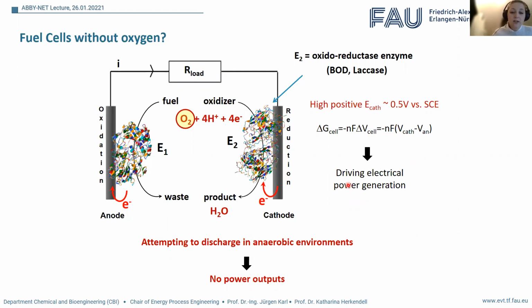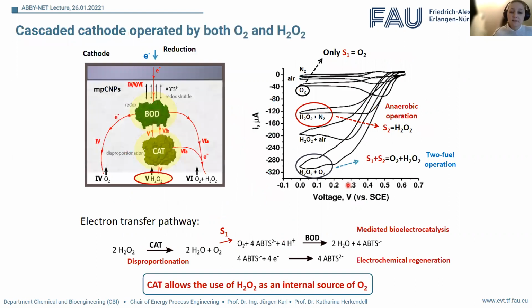And we implemented another cascaded enzyme, in this case catalase, that would cooperate very well in case there was no oxygen and instead hydrogen peroxide. So we would have a cascaded reaction of hydrogen peroxide with the catalase first, disproportionation to water and oxygen, which would locally generate such high oxygen concentrations that we could not only yield very effective oxygen reduction, but we could even operate much more effectively than with a purely oxygen-based system.